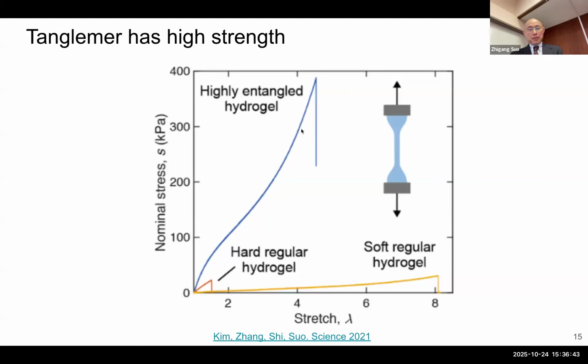So now this is probably what most mechanical engineers love. This is stress and stretch. However you prepare your regular hydrogel, you can make it stiff by putting in a lot of crosslinks, or very soft with very few crosslinks. Your stress-strain curve is just way below, by orders of magnitude, the highly entangled hydrogel. So this material really is good by ordinary measurement.